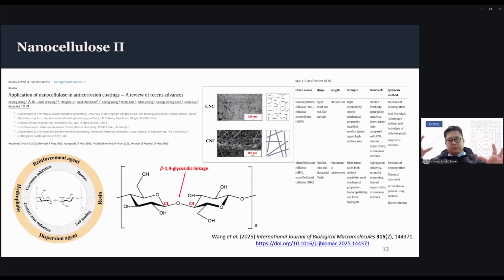What actually happens is when you take them out, say from the solvent that you keep them in, if you dry them out, they can start agglomerating. So if you don't do some functionalization, as often seen in many of these early reports, they start agglomerating and are not very well dispersed inside the coating. When they're not well dispersed, that limits the performance of this nanocellulose in the coatings.